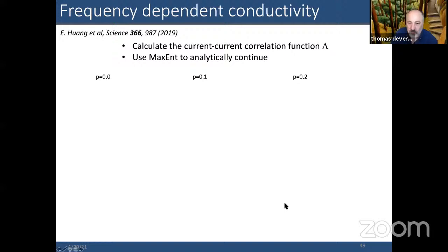So here what we do is we calculate a current-current correlation function, which lives in Matsubara frequency or imaginary time. And to get it to give us a conductivity, we have to do what's called analytic continuation. That's using maximum entropy to be able to do that. As you know, maximum entropy is a bit like a black box. However, we can be fairly confident, by doing many, many checks, that the results we're getting are at least on grand scales can be trusted.